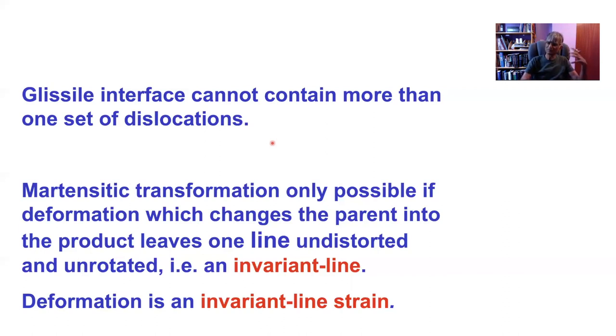So, for example, I was just mentioning monoclinic nickel doesn't exist, but we can do a calculation easily of the stability of that crystal structure using first principles, and then speculate as to whether we could produce martensitic transformation between those two. Or more generally, if you're looking at other alloys which do exist, such as uranium, we get many different crystal structures, and we can work out whether or not martensitic transformation is possible between the different allotropic forms.